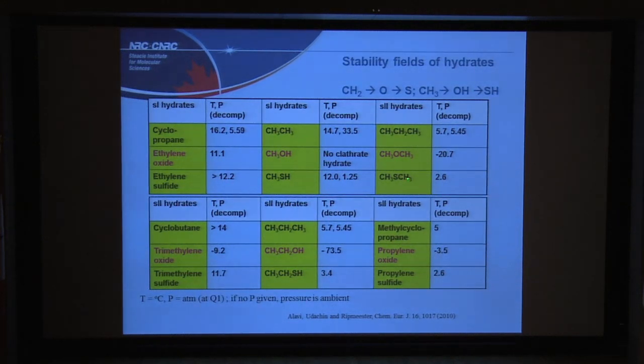But you can see that in the center row in each of these cases, the stability field of the gas is far less than that of its neighbors. And what this says is that all these gases that contain oxygen are different from the other ones. And this is clearly recognizable if you look at a table like this. So obviously, chemistry is important. It's been many years since a chart like this was known, but people have concentrated on dealing with the hydrocarbons, of course, and not worried too much how their models worked for other guests.